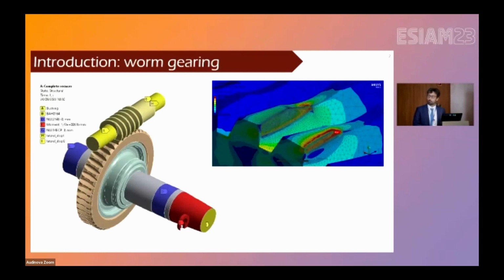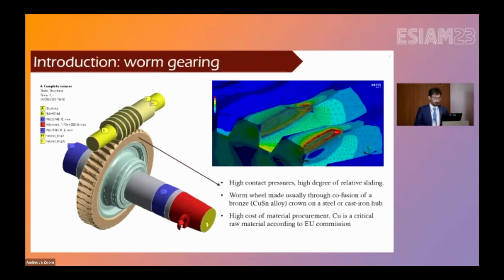a screw and in a worm wheel, producing a very complicated contact pattern characterized by high contact pressures and by a high degree of relative sliding. For these reasons, the worm wheel is currently made of bronze. Bronze is a copper alloy with a high content of copper, 90% above. But copper represents a great limitation for these gear sets, because copper was declared by the European Commission a critical raw material, with a very severe perspective of shortage in the near future. So there is a quest for replacing, or at least reducing as much as possible, the use of copper in these components.